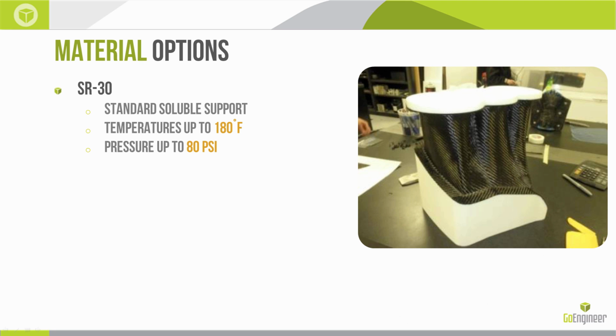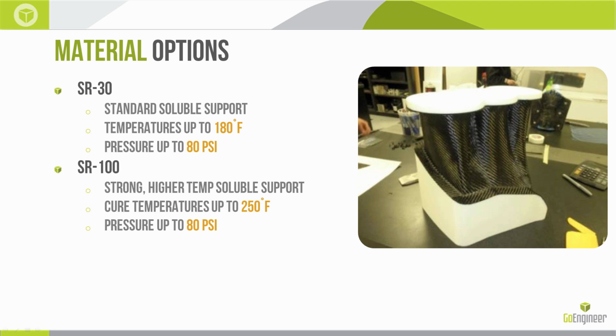So what are our material options? We keep talking about soluble materials. What sort of materials are we talking about? Well, the first is called SR30, and this is the Stratasys standard soluble support. It is a soluble support that's used on the ABS materials, ASA, most of the non-high heat or high mechanical strength materials. We can use this in temperatures up to 180 degrees Fahrenheit. That's the stated heat deflection temperature, and that's a temperature that you would want to stay at or under during the curing process. And if you're going to put this in an autoclave, you'd want to keep it at or under about 80 psi. The next option here is SR100. SR100 is going to be the stronger, higher temp, but still soluble support material. It's good to 250 degrees Fahrenheit, but the pressure is still the same. You don't really want to go above 80 psi on the pressure if this is in an autoclave. Both of these materials can be vacuum bagged and pulled full vacuum, but if it's in an autoclave, keep it at or under 80 psi.